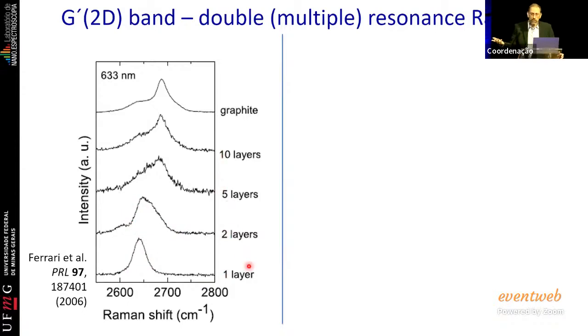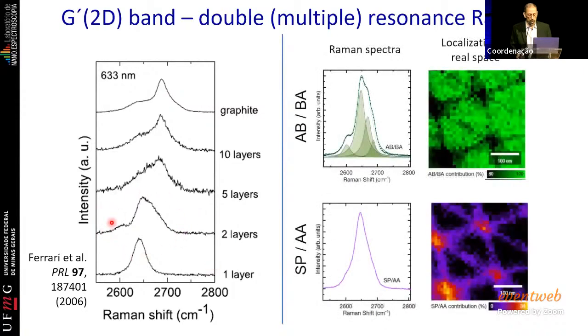And this is very important for all the developments of, let's say, graphene devices, okay? Because you may want one layer, two layers, or rotated layers, etc. And they demonstrated that when you have bilayer graphene with the regular AB stacking, the shape of this band is like this, okay? So when we do nano optics, we do see shapes that are very much like this one in AB stacked bilayer, and we have shapes that are a little bit backwards, but look more like single layer or uncoupled bilayer graphene.